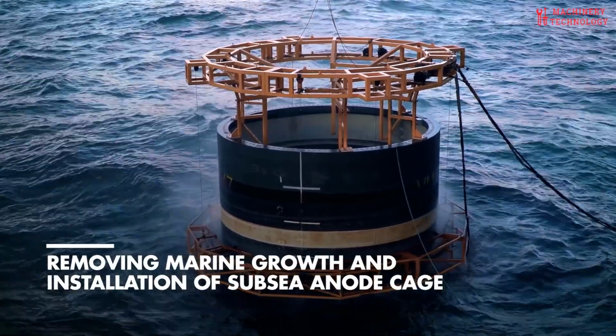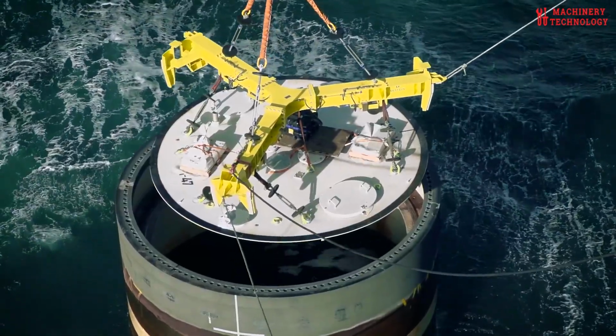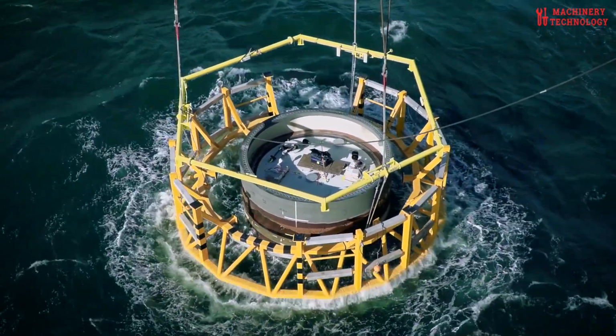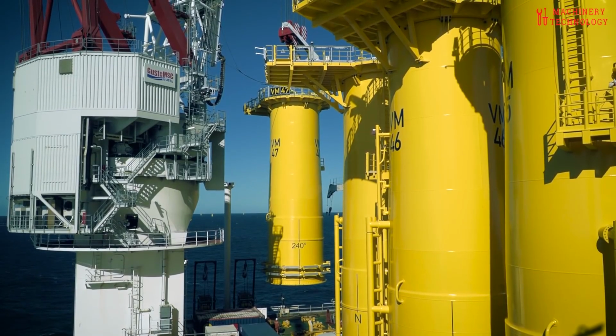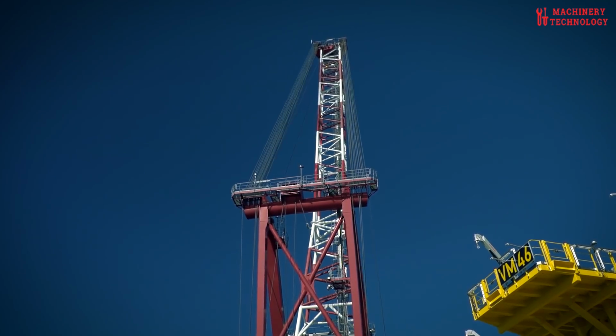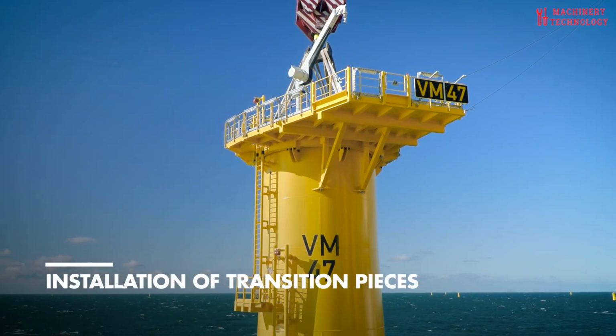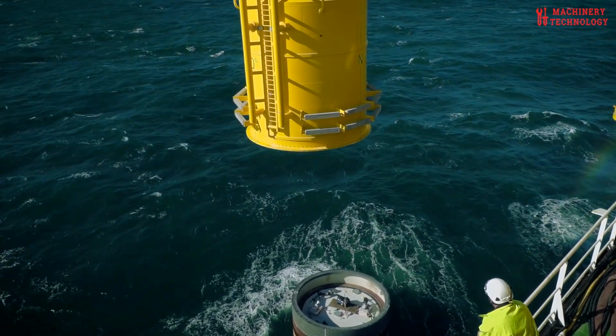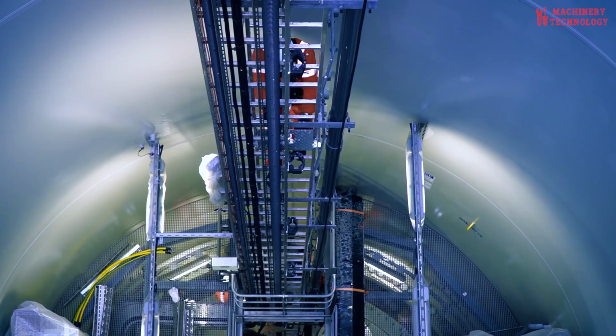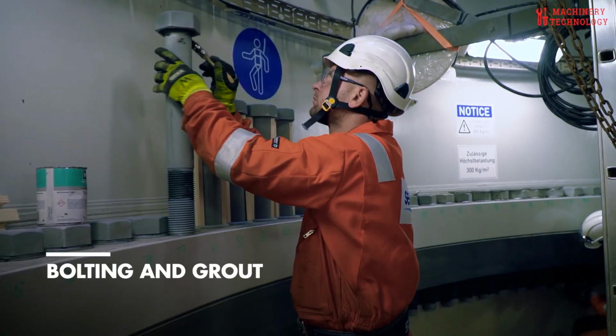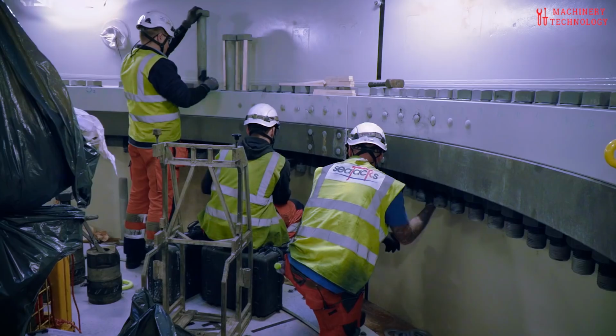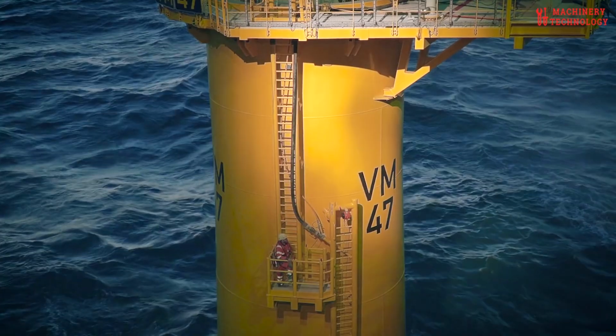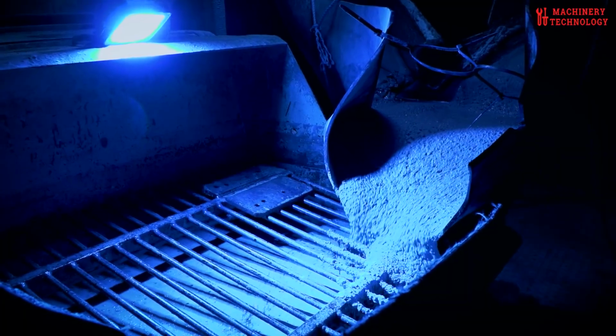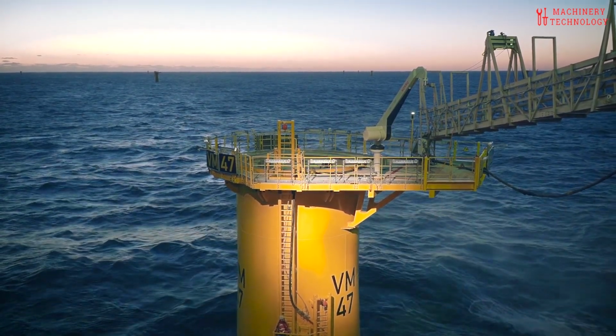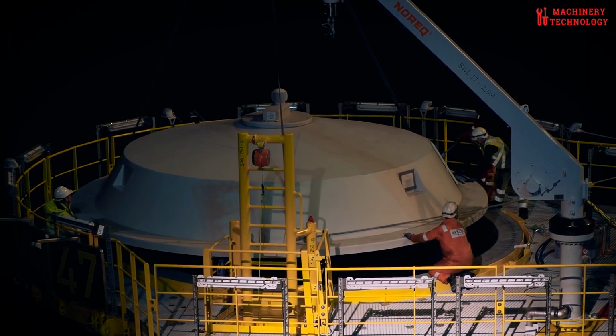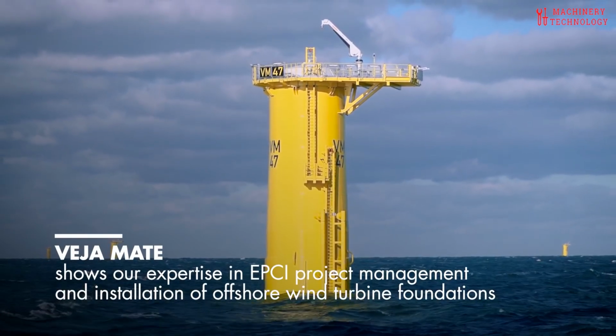Once the pile is deeply embedded, a transition piece, pre-fitted with necessary features such as boat landing structures, cathodic protection, cable ducts for subsea cables, and a flange for the turbine tower, is attached. The hollow center of the pile is then cleared of sand and water and filled with concrete to secure stability. Finally, an additional layer of larger stones, with diameters up to 0.5 meters, is placed around the seabed surface, providing long-term erosion protection and structural durability. This advanced monopile construction method enables robust and lasting support for offshore wind turbines in dynamic marine environments.